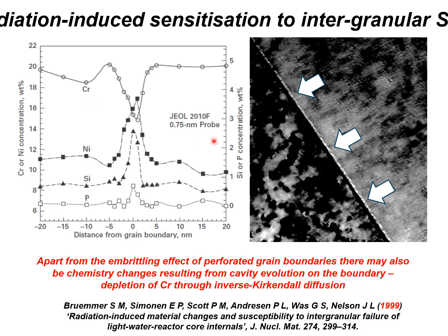So in the case of irradiation, when you have radiation and a vacancy sink, what that means is that you'll get preferential depletion of chromium from the vacancy sink. The same applies to iron, by the way, because they're equally fast diffusers. But nickel and other elements like tin, it's not here, but I guess it's silicon, they're not as rapid.